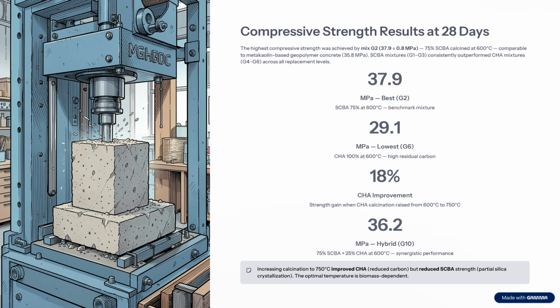CHA 100% at 600 centigrade shows higher residual carbon and the lowest mechanical strength, around 29.1 megapascal, and CHA improvement around 18%. The hybrid G10 shows a mechanical strength around 36.2. From that we can see that increasing calcination to 750 degrees Celsius improves CHA by reducing carbon, but reduces SCBA strength due to the particle size and partial silica crystallization. The optimal temperature is biomass dependent.